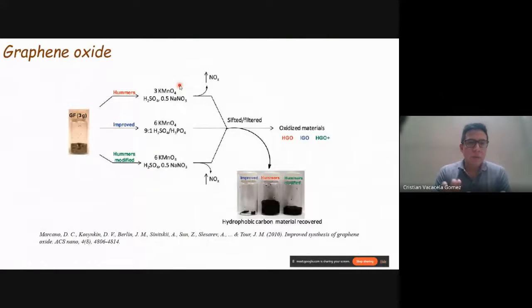Then, there are a lot of techniques just within the graphene oxide process for synthesizing this type of sample. For example, the common method is Hummers' method, the improved method, and Hummers' modified method. This is a chemical process commonly used to prepare graphene oxide samples for different applications. In this chemical process, we can identify potassium permanganate and also sulfuric acid. But what is the difference between the Hummers' and Hummers' modified methods compared with the improved method? The improved method was proposed in 2010 by Marcano. Here they use sodium nitrate in Hummers' modified method, but in the improved method they use orthophosphoric acid. Anyway, using graphite, they produce graphene oxide.